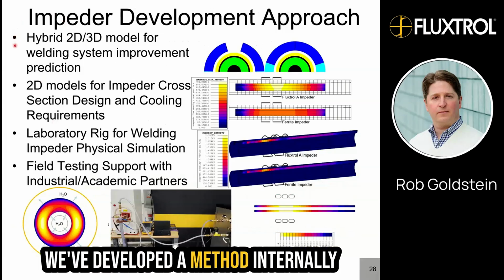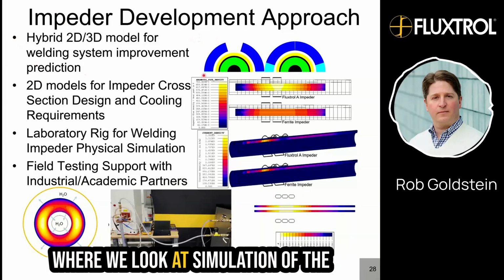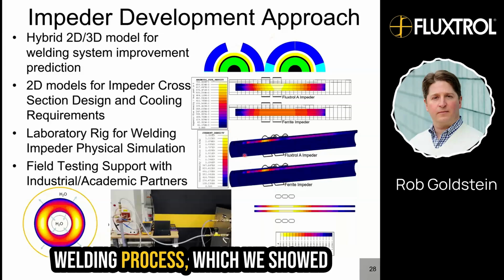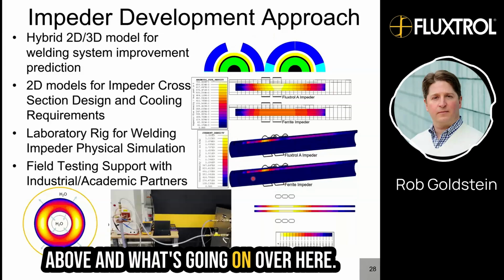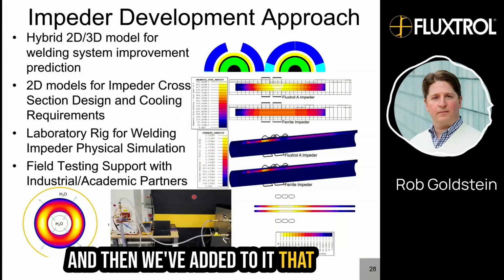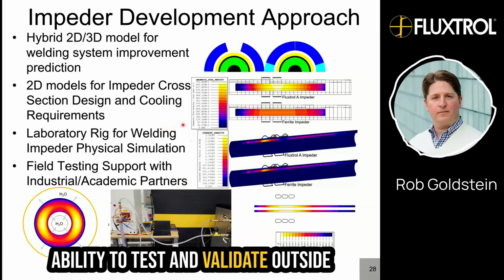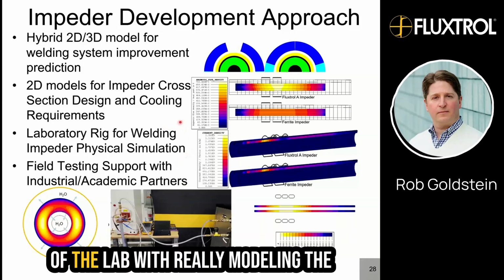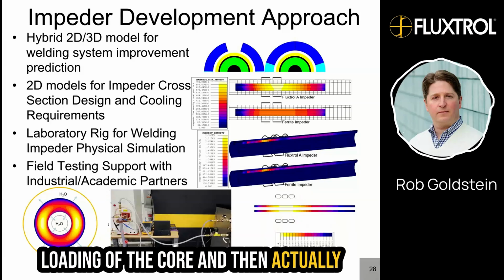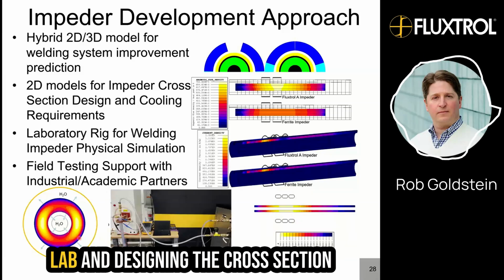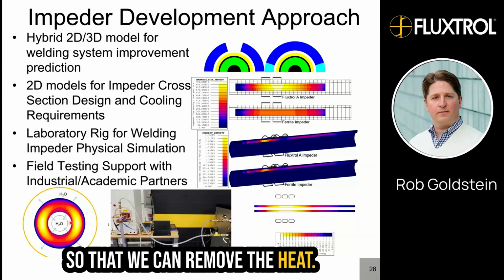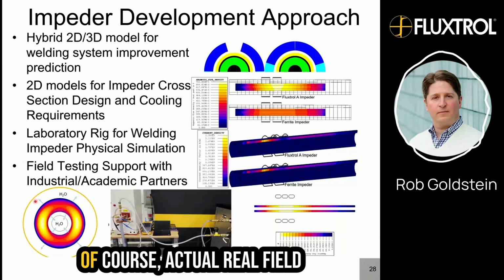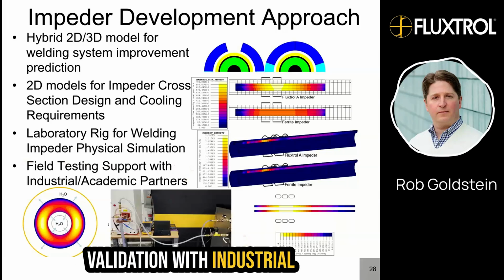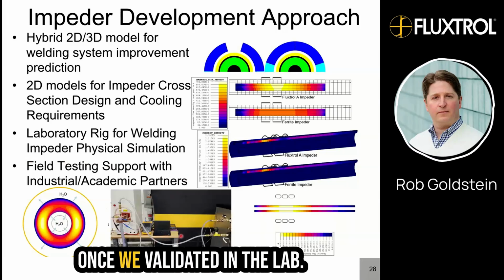We've developed a method internally where we look at simulation of the welding process, which we showed above, and what's going on over here. And then we've added to it that ability to test and validate outside of the lab, with really modeling the loading of the core and then actually testing the loading of the core in the lab, and design the cross section so that we can remove the heat. And then the last portion is, of course, actual real field validation with industrial and academic partners of our designs once we validate it in the lab.